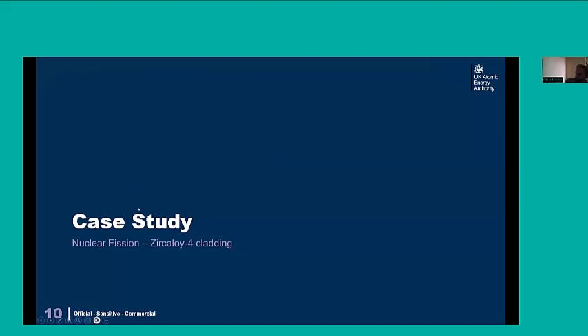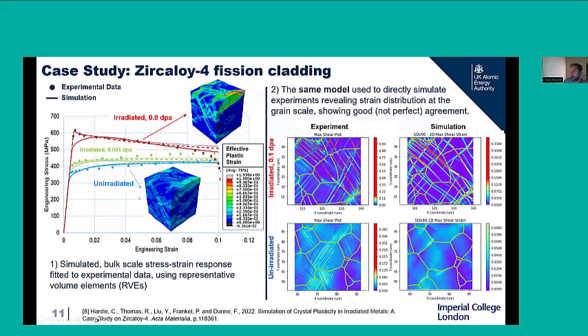And so this was an early idea, and the thing that gave it traction at UKAEA was this case study that we ran. Now this is on zircaloy 4, which is a fission cladding material, but due to the wealth of data available at the time on this, we decided to run a case study on this. So on the left, we can see in the data points stress strain responses measured by experiment of zircaloy 4 in the unirradiated, the slightly irradiated or lightly irradiated, and then the more heavily irradiated condition.